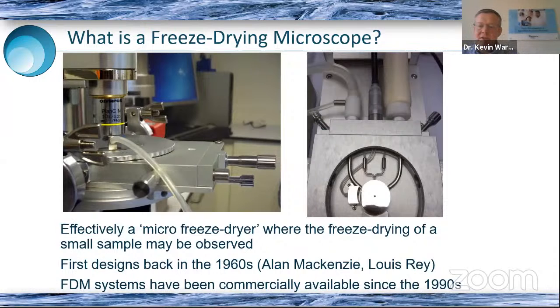And effectively, a freeze drying microscope is a mini freeze dryer or a micro freeze dryer. And here we have our freeze drying stage, which is on the left-hand diagram. It sits onto the platform of a microscope or an imaging station, and we can view the sample from above. And on the right, it shows the inside of the chamber in more detail. We can see that it centers around this cylindrical silver block in the center, which is effectively like a small freeze dryer shelf, if you like. And this is controlled by a cooling and heating mechanism. The cooling is through liquid nitrogen, which comes through this tube on the right, insulated tube from a dewar, and it gets circulated through the block and then out the other side.